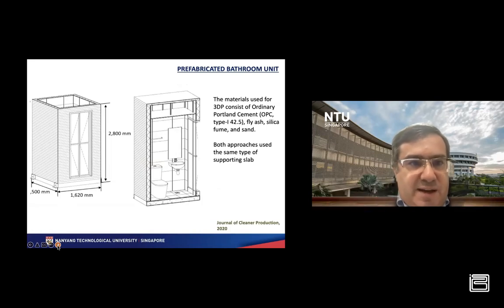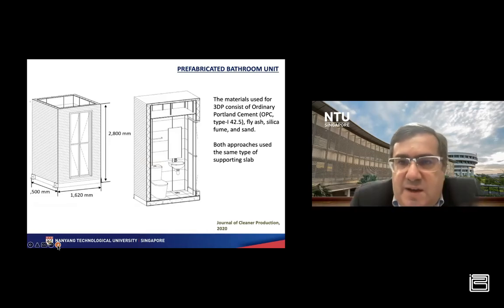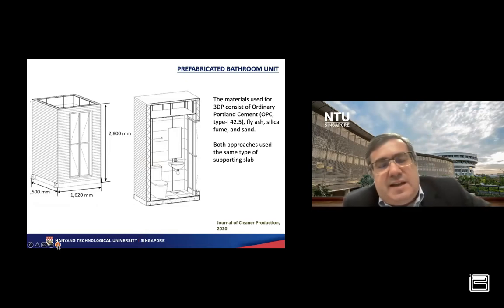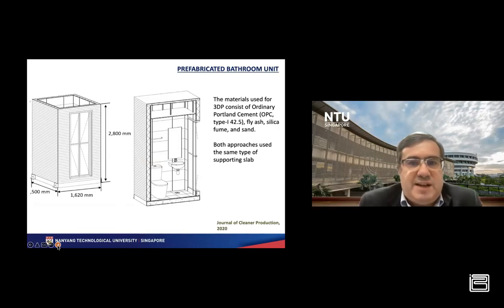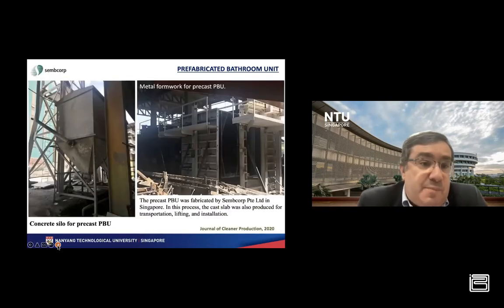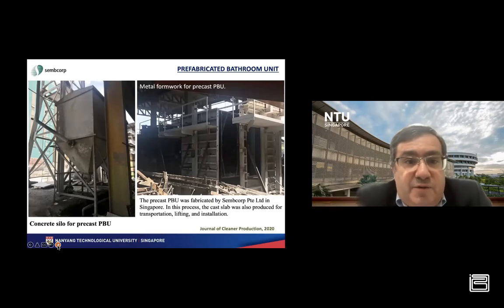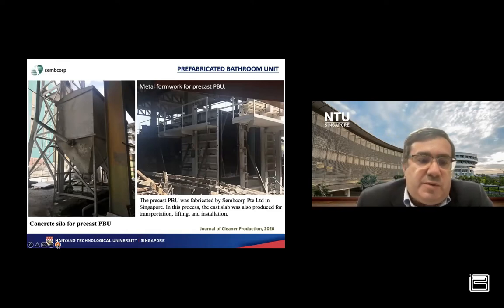For the precast, we use standard materials. For the 3D printing, we use a proprietary material. I cannot provide too much detail about the materials due to commercialization issues, but it roughly consisted of ordinary Portland cement, fly ash, silica fume, and sand. And in both cases, 3D printing and precast, we use the same type of supporting slab. The precast PBU was fabricated by our industrial partner, Sembcorp, and we were responsible for the 3D printed PBU.